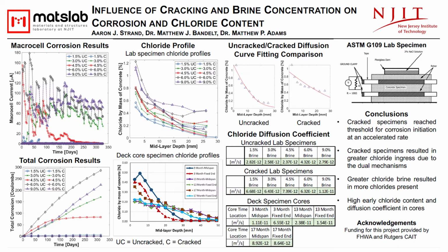In this test method, the chloride concentration is held constant at 3% by weight, though for this testing, 5 different chloride brines from 1.5 to 9% were used. This was done to simulate the impact that different concentrations of brine from factors like the application amount, the deck surface topography, and weather conditions have on bridge decks. To measure the impact of cracks, each brine concentration had one specimen in the uncracked condition and another in the cracked condition.